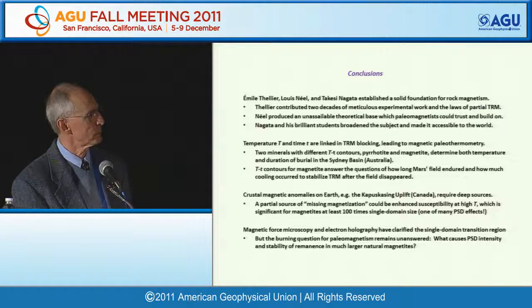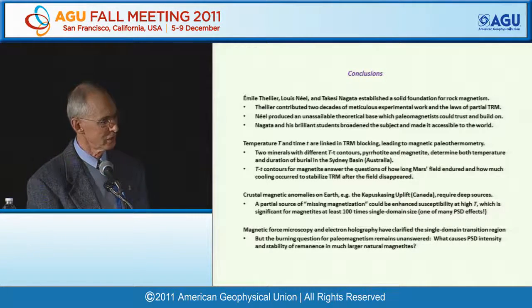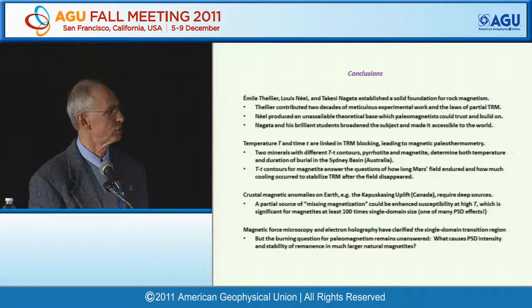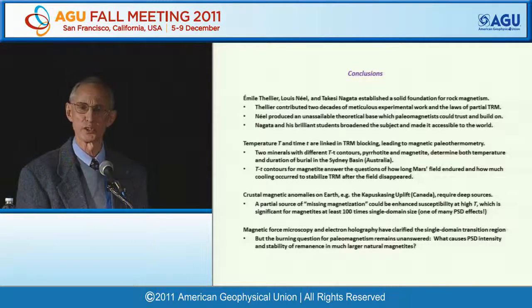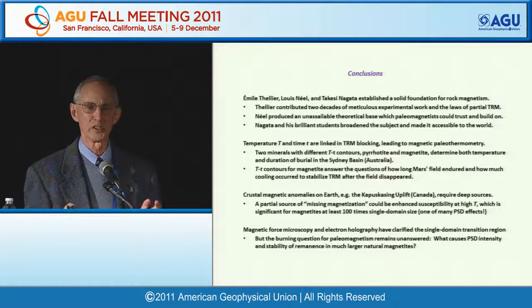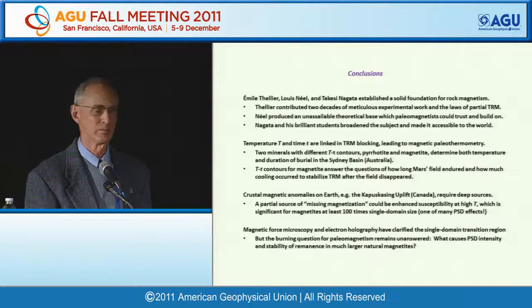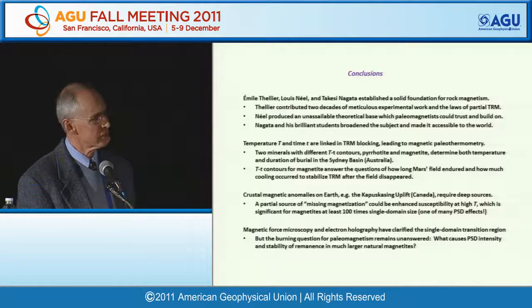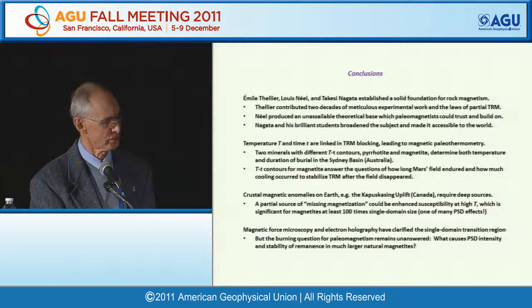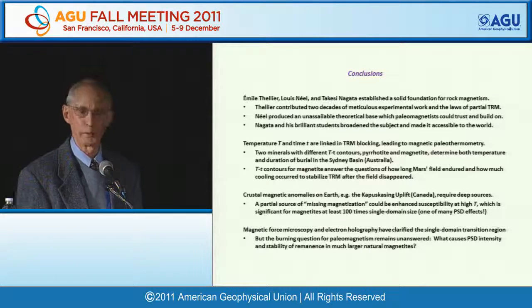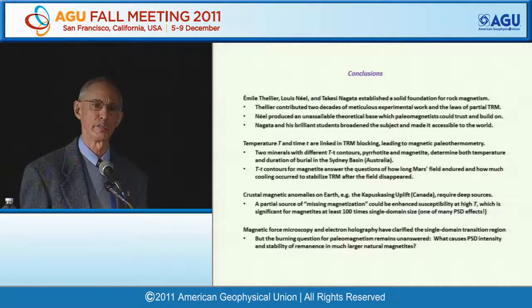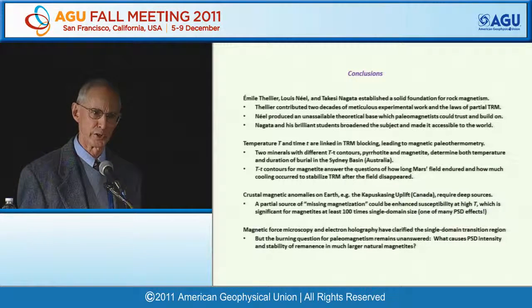In applications, temperature T and time little t are linked in TRM blocking, allowing us to do magnetic paleothermometry. If you have two minerals with different time-temperature contours, you can determine simultaneously times and temperatures of burial. Looking on a big scale at a planet-sized question, we can make predictions about how long Mars' field must have endured and how much cooling would have been required for its crust before the field turned off in order to stabilize that TRM until the present day.